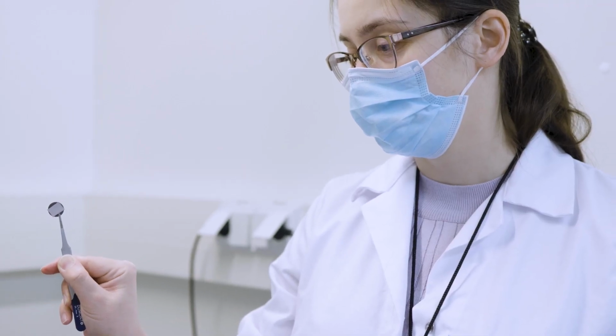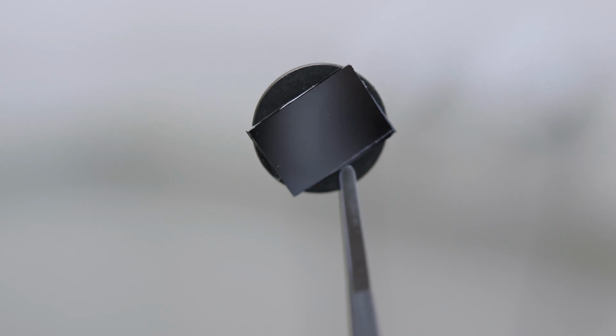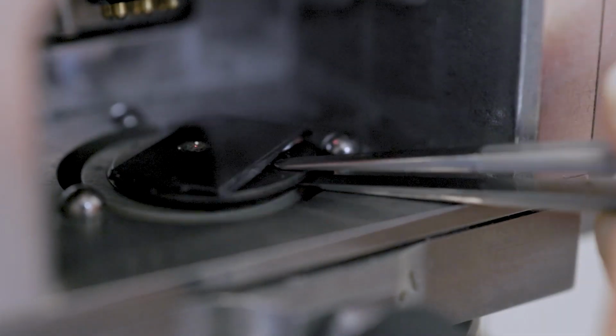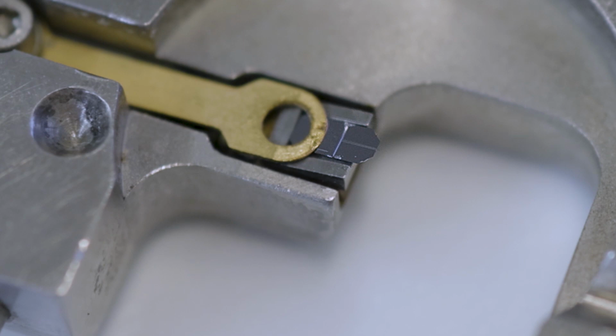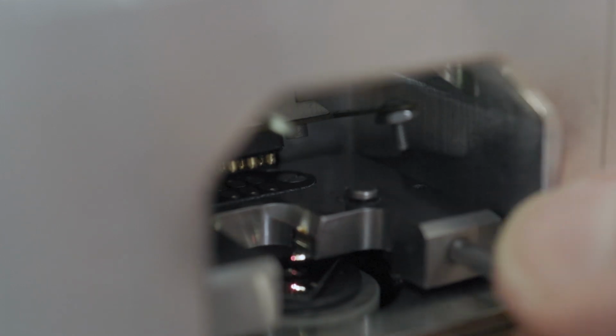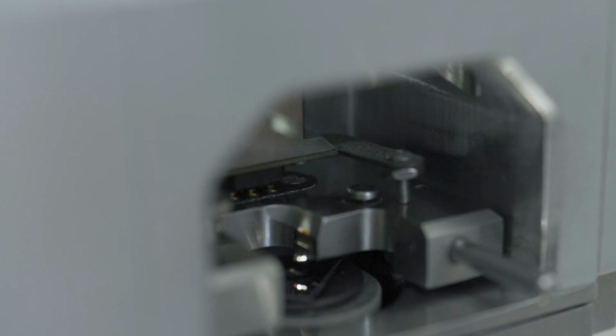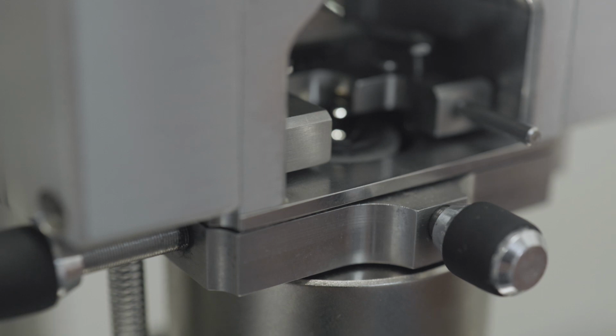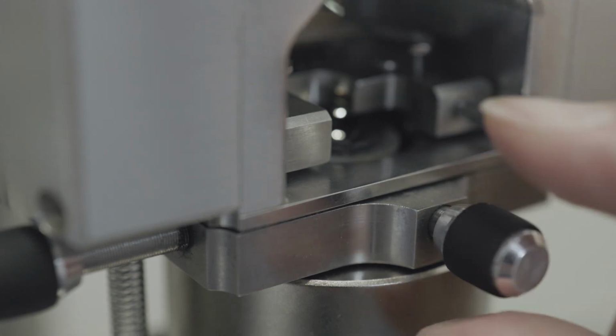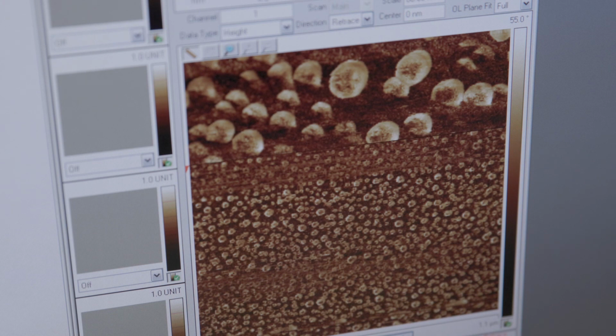Working principle of AFM is scanning of the surface with a scanning probe, which consists of cantilever and sharp tip. Sharp tip interacts with the surface and deflects a cantilever. Deflection of cantilever is recorded by the laser, which reflects from the cantilever and hits the photodetector. This data is used for the topography imaging. In our work, we usually use AFM in tapping mode.